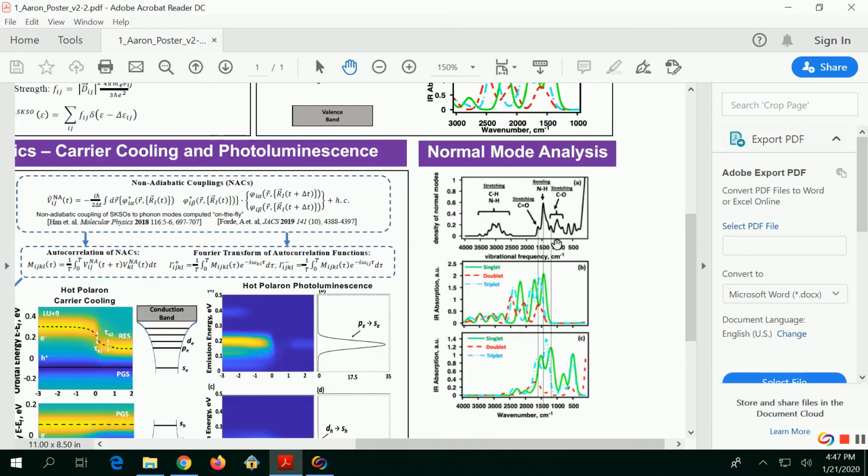Then when you consider the negative polaron, its transition energies are higher than what's provided by the perovskite lattice itself, but it also gains contributions from the surface vibrations from the ligands, which are the CO stretching from the carboxylates and from the amine.